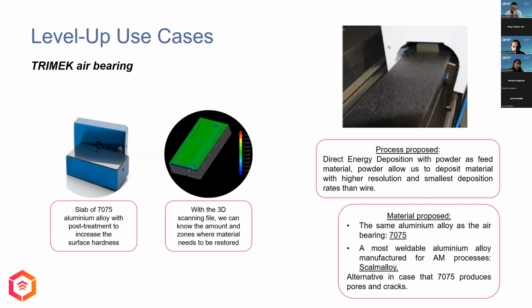And the last use case that I developed was the remanufacturing of an air bearing belonging to a coordinate measuring machine. The wear of the bearing surface causes a waste of money in compressed air during the use of the machine, but replacing the part is also really expensive because the material used for the part is an alloy usually used in aeronautics. The reason is that a hard material is needed, but also light, to decrease the consumption of compressed air.